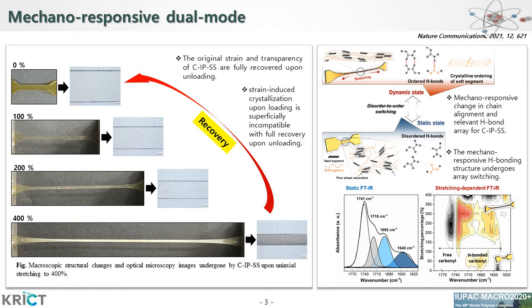The FTIR spectrum of CIPSS shows 4 bands associated with carbonyl groups in stretching mode. CIPSS has a relatively high degree of disorder with regard to its non-crystalline hard segments and a high concentration of hydrogen bond-free carbonyl groups. Uniaxial stretching in the dynamic state enhances the degree of hydrogen bond ordering, leading to an increase in crystallinity and a decrease in the concentration of carbonyl groups that are not hydrogen bonded, which is well represented by a 2D gradient FTIR map.